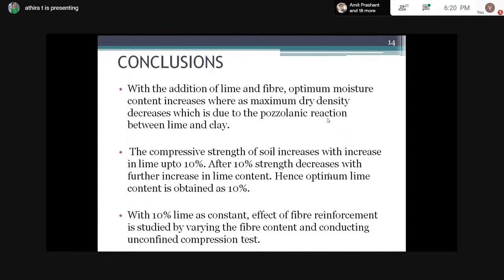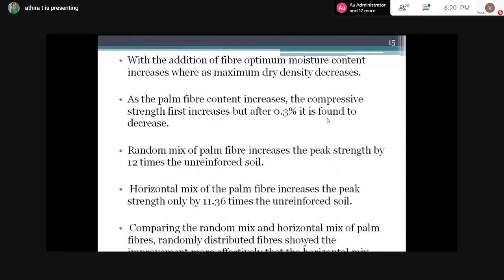With 10% lime as constant, effect of fiber reinforcement is studied by varying the fiber content and conducting unconfined compression test. With the addition of fiber, optimum moisture content increases, whereas maximum dry density decreases. As the palm fiber content increases, the compressive strength first increases, but after 0.3% it is found to decrease.